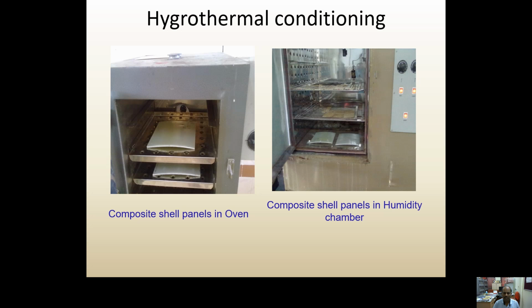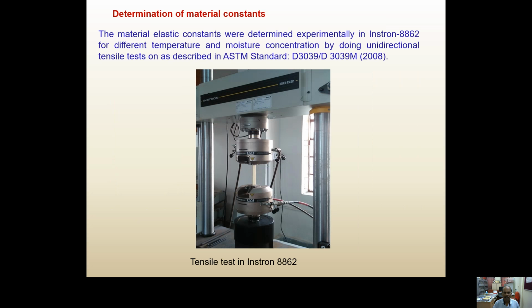The specimens are treated in an oven for increase in temperature. The specimens are treated to moisture in a humidity chamber. Then the material elastic constants were determined experimentally in Instron 8862 for different temperature and moisture concentration by tensile test as described in ASTM standard D3039.